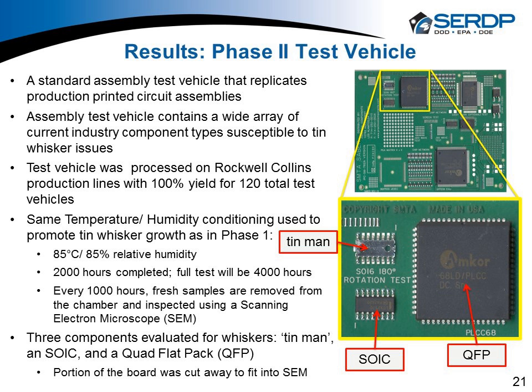So I guess we'll see the results, but I just want to ask a question. By using tin lead solder, are you stacking the cards against whisker formation? We were here, but as you remember from phase one, this Tinman doesn't solder nearly as well as the SOIC, because bright acid tin is kind of a lousy surface to solder to. So the tops of the leads here, they were good, and I should have mentioned this too. We only soldered the four corners on Tinman. So the leads in between the four corners, there was no solder.